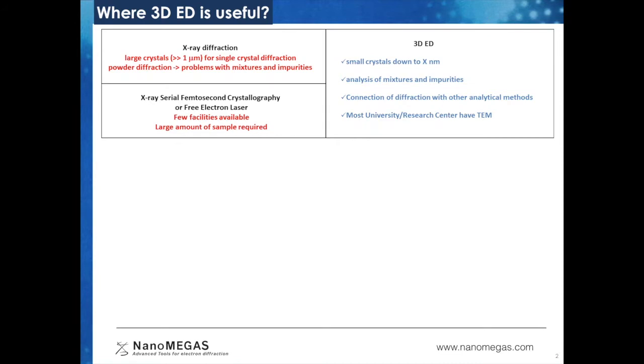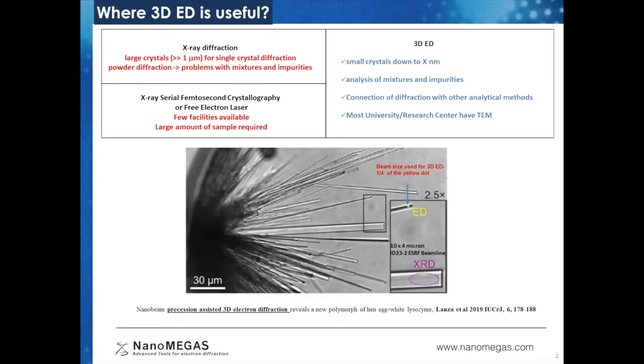Now let me show you an example from recent publications to better understand what size of crystal can be used in the TEM. As you can see in the magnified image of the crystal, the purple colored circle is required for doing X-ray diffraction data collection in a microfocus beamline at ESRF. And on the top, you can see the yellow dot, which shows the size of the crystals required for 3D electron diffraction. It shows you what size of crystals you really require for a 3D electron diffraction study.